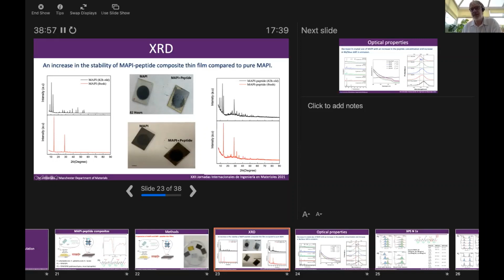And again, if we look at the XRD, we do start to see peaks arising here now due to the presence of lead iodide, but maybe that's due to the stuff which wasn't encapsulated. But we do still see fairly strong methylammonium lead iodide peaks, this one and this one here.